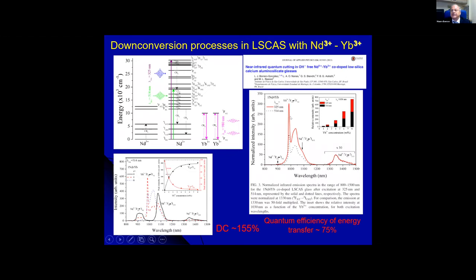For example, we did this work, it's already published in this paper, where we show that we can convert 155%, it means one visible photon can generate 1.5 photons in the near infrared. So this is the downconversion process with an efficiency of 75% in this glass. The important aspect of the glass to show this is the phonon energy, as I said before, and secondly,